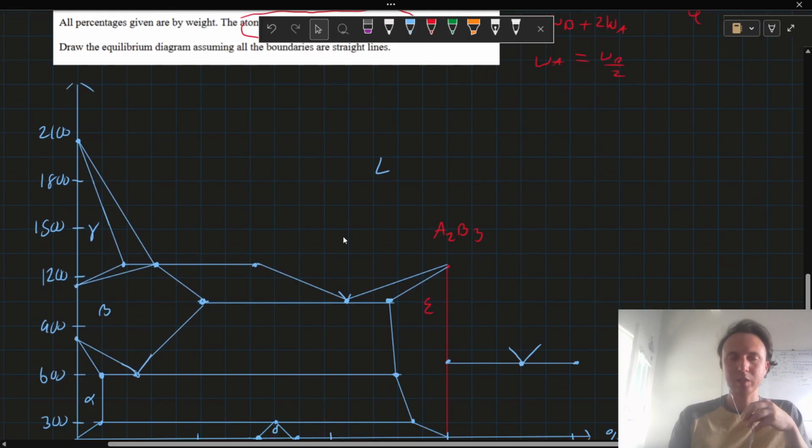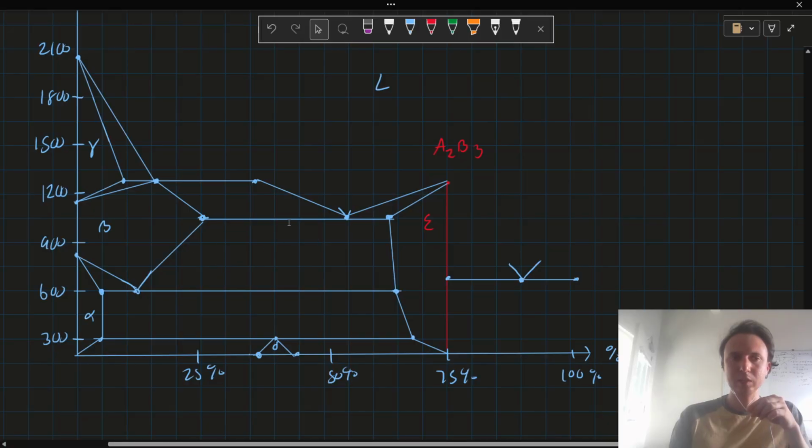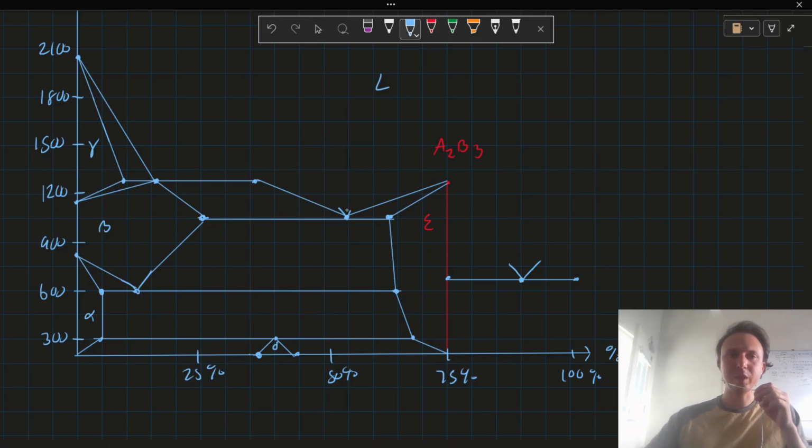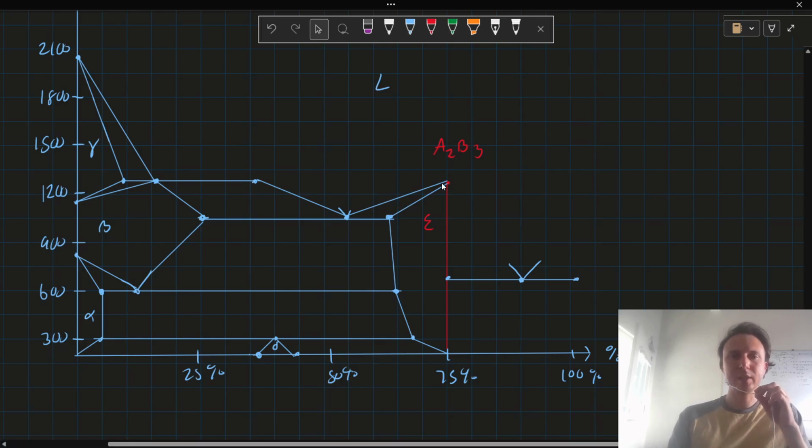And then we have the eutectic at 1000 Celsius. It'll go from 75% beta, epsilon. So 1000 Celsius will be this one here. And it's eutectic. Yep, the linears go up. And it has beta and epsilon. And it goes from liquid to, so this is the beta plus epsilon region. This is beta plus liquid, and this is liquid plus epsilon. All right, so that checks out.